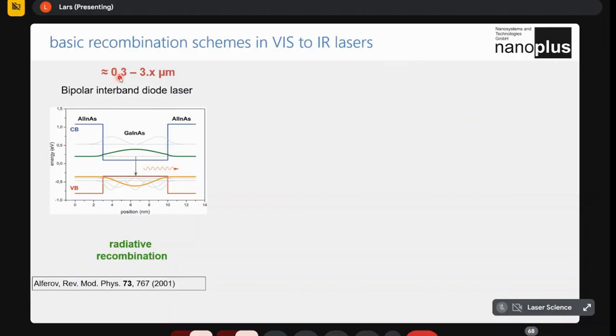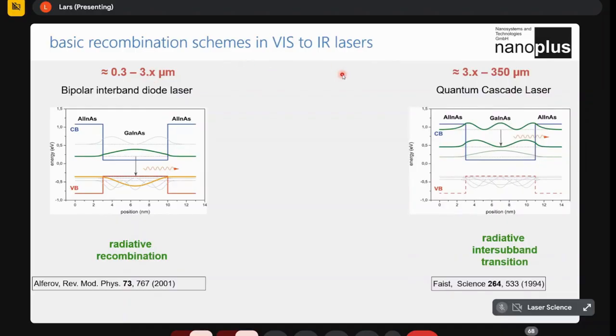You can do diode lasers down to something like 300 nanometers up to 3-point-something micrometers. You can even squeeze that up to, I believe, 6 or 7 micrometers with lead salt lasers. But in that case, you need a lot of cooling, down to liquid nitrogen. So to go to higher wavelengths, the quantum cascade laser was developed and invented in 1994 by Jerome Faist's group. Here you can see the transition is only happening in the conducting band. So the electron jumps within the conducting band, within the same quantum well, from an upper state to a lower state, emitting a photon. This has a lot less energy than this transition. So here you can go up to the terahertz regime in principle.